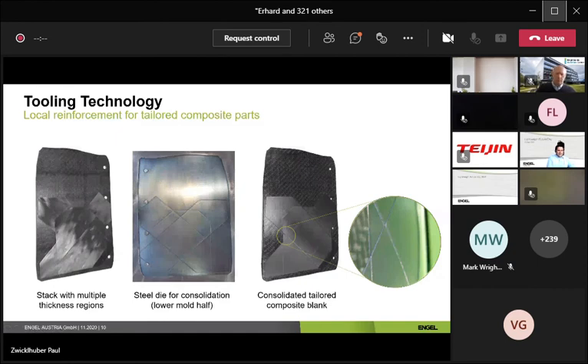On the left side, you can see such a layer produced at the tape stacking unit. In this case, it consists of an organo sheet with glass fiber, and 6 tapes with carbon fiber. The picture on the right shows the consolidated part, which is ready for further processing steps. You can also see the different wall thickness, and it's perfectly consolidated.